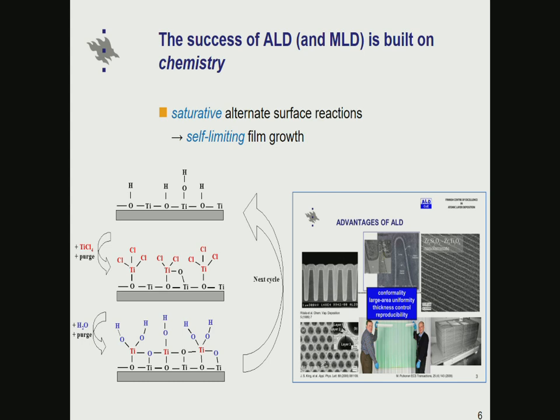This morning made it very clear that the success of ALD and also MLD in the future will be built on chemistry. So there are lots of very nice features about ALD: conformality, large area uniformity, thickness control, and so on, which are built on the self-limiting saturative surface reactions, which means that to exploit these benefits for a given material, one always needs to identify and find the right kind of precursors which are fulfilling these requirements for the ALD precursors. So meaning that they are undergoing these saturative surface reactions, because only that makes the film growth self-limiting, and only self-limiting film growth then translates into these advantages, features of ALD.